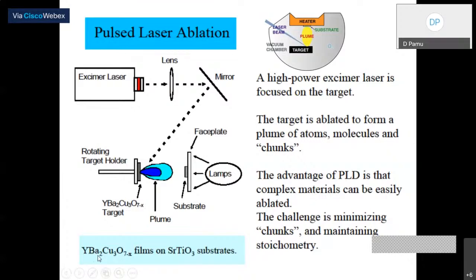Whenever the stoichiometry is very crucial, in that context, you will go for pulsed laser deposition or laser ablation. That means I want exactly 1 yttrium atom, 2 barium atoms, 3 copper atoms, and 7 oxygen atoms. If there is a slight deficiency of oxygen, this material will not behave like a superconductor. But what is the laser going to do here? A high power excimer laser is focused on the target. So your laser beam is coming, which is focused onto the target. This is your target here.